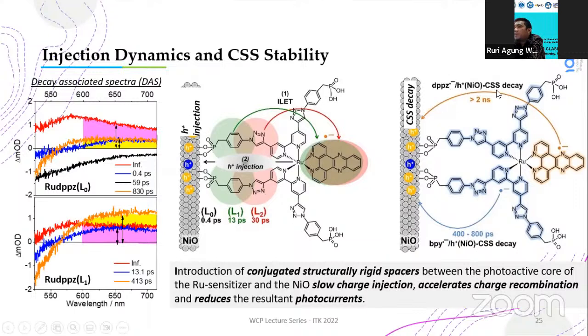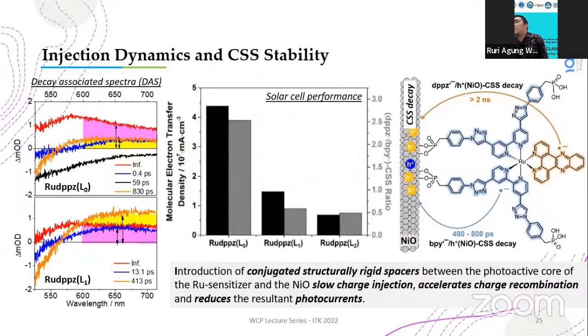And then this is the time scale of charge separated states decay. You can just easily see the number there. And this is the solar cells performance. Because of the screening of hole injections by the charge accumulations on the dppz ligands, here we can see that the molecular electron transfer density at the dye-sensitized nickel oxide interface is higher for ruthenium L0 without the linkers. And the addition of the linkers will harm the hole injection and also lower the performance of the dye-sensitized photocathodes.